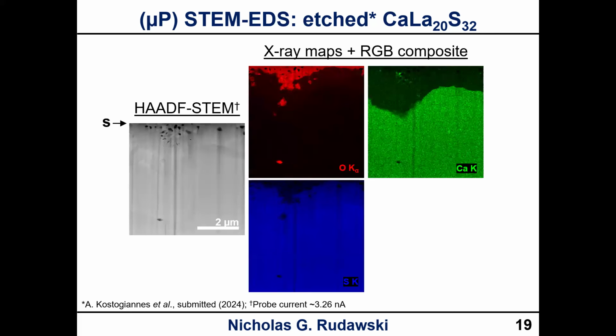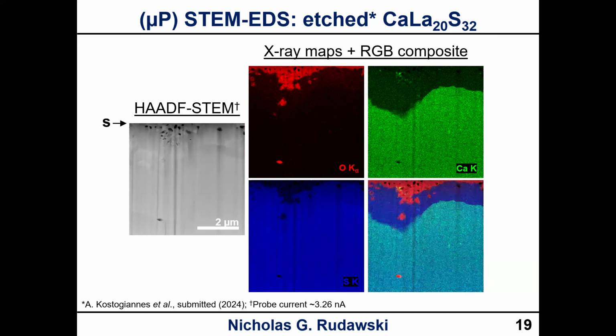But when we do the EDS mapping, what we see is that we have three clear regions in the sample. So we have one that is very rich in oxygen, and then we have another that is rich in sulfur, but not calcium or oxygen. And then we have another that is rich in sulfur and calcium. Okay. I didn't show the lanthanum because the lanthanum was basically the same everywhere. Okay. If we overlay these, we can see this very clearly, right? So we have these three zones here.